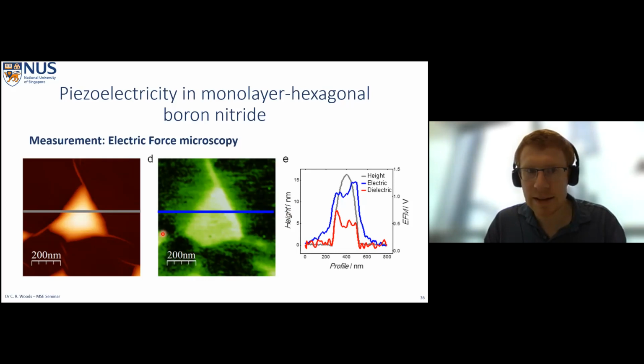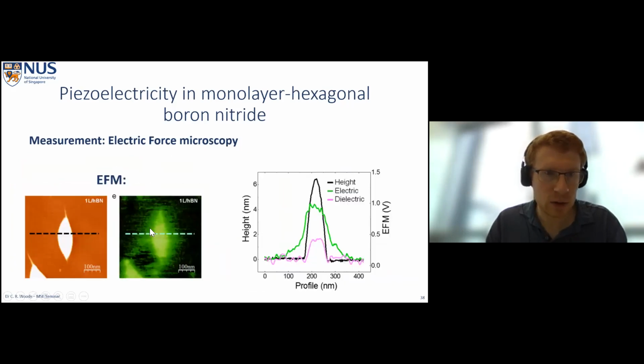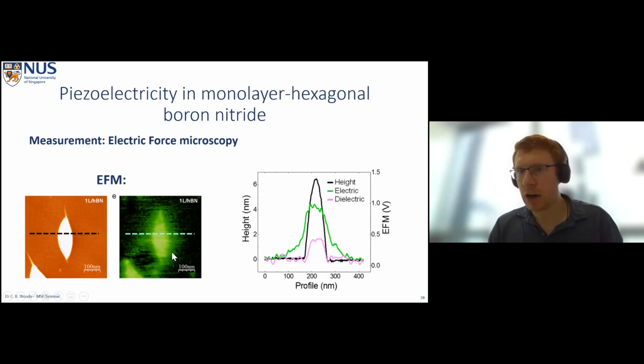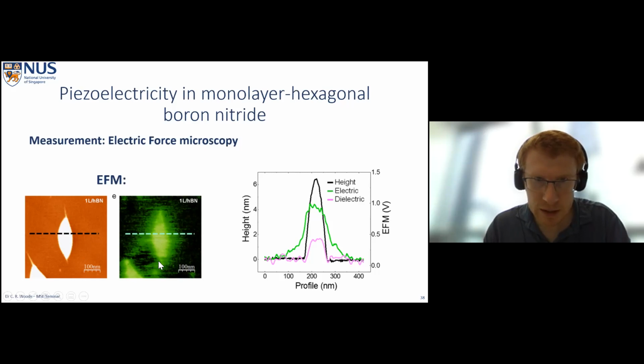Now, how do we exclude the idea of, say, contamination or things like that? In that case, we just have to look at the topography signal and say that we don't have any serious contamination. And we can look at the map of EFM to see that this follows the shape of the bubble. The black curve here, once we leave the bubble, has 0 roughness. Also, when we look at the map of the EFM signal, if we had some charge trap or some local charging, we would not expect it to so precisely follow the edge of the bubbles. Does that answer your question?